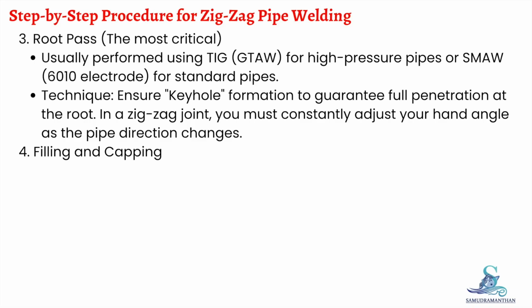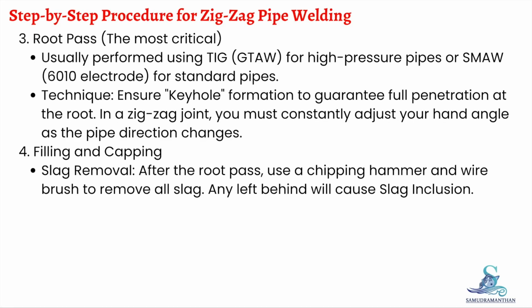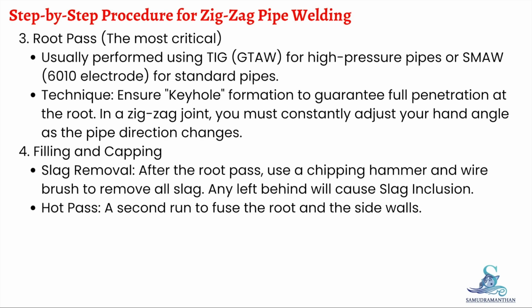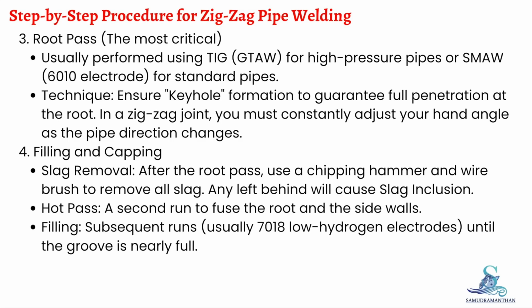Filling and capping. Slag removal: after the root pass, use a chipping hammer and wire brush to remove all slag. Any left behind will cause slag inclusion. Hot pass, a second run to fuse the root and the sidewalls. Filling, subsequent runs, usually 7018 low hydrogen electrodes, until the groove is nearly full.